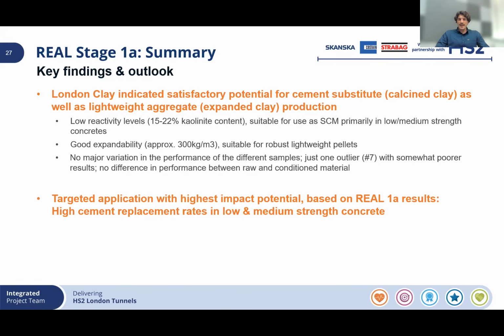So the summary for stage 1A was that we obtained satisfactory results in terms of using London clay as a cement substitution, but also if we want to produce lightweight aggregate, it is also possible. We knew that London clay had relatively low kaolinite content. We confirmed that with tests, but we also showed that it's not a limitation in terms of using in concrete. So we decided to start targeting highest impact potential applications, such as development of mixes with high replacement rates and low strengths. Next slide, please.